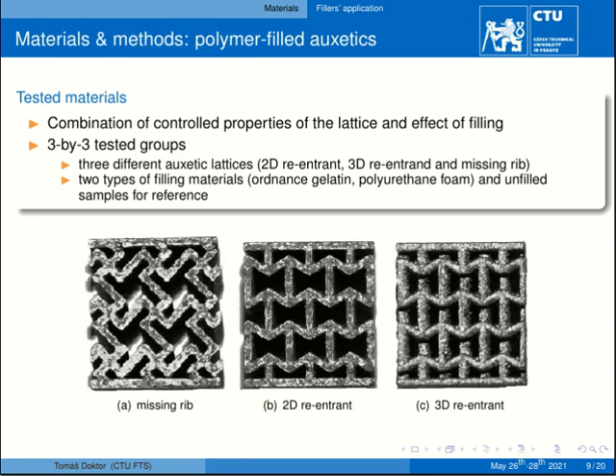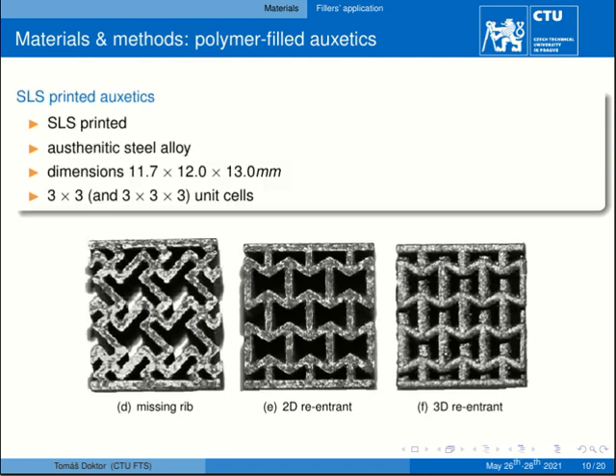In this research we tested a combination of three types of auxetics. Two of them are two-dimensional auxetics and one is a three-dimensional auxetic, and these three types of auxetics were then filled by two types of filling material, ordnance gelatin and polyurethane foam, and the last group was kept unfilled for reference. These samples were manufactured using selective laser sintering from austenitic steel alloy, and the design of the samples was selected in order to achieve at least one unit cell inside the structure